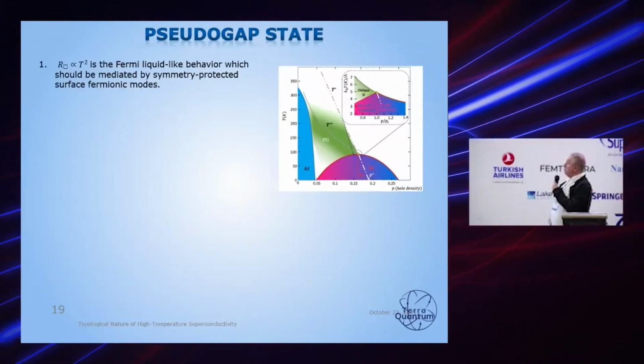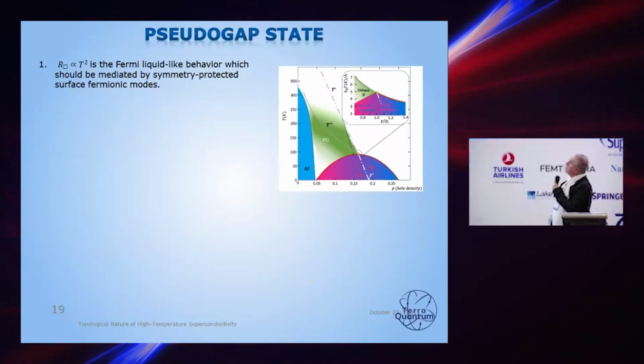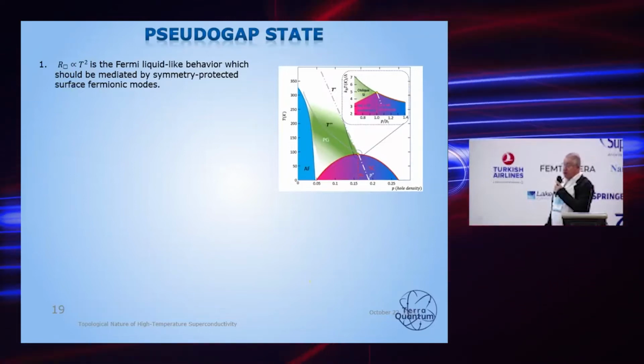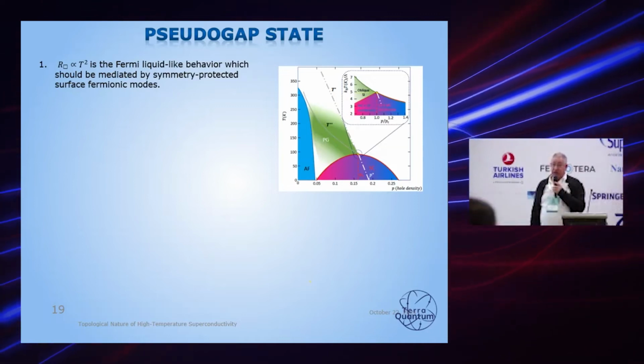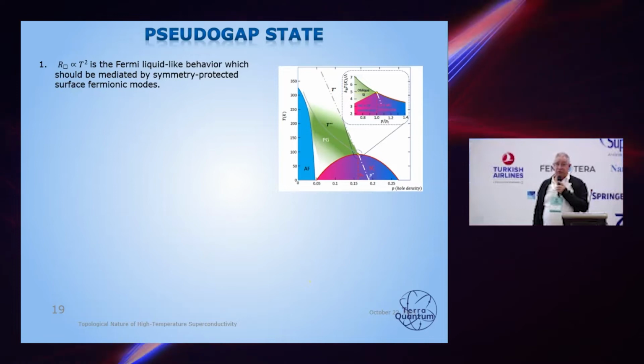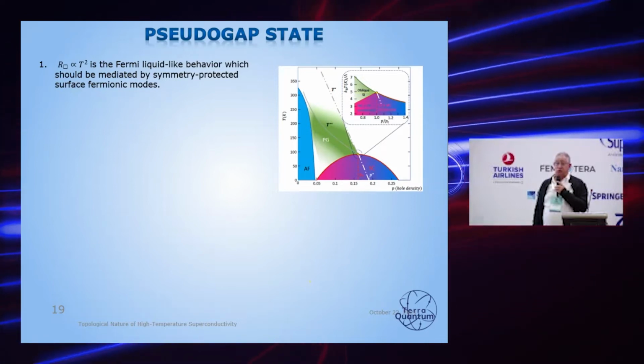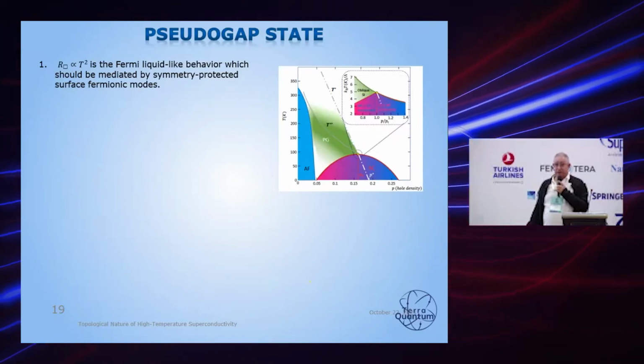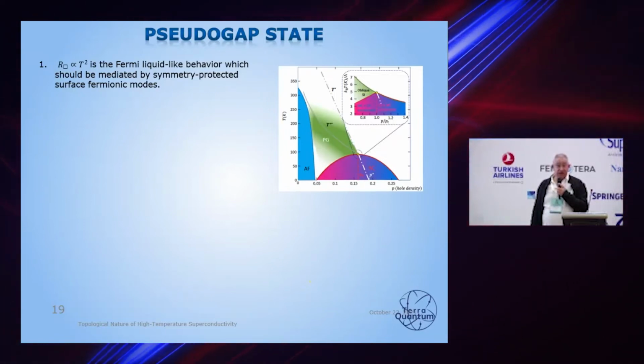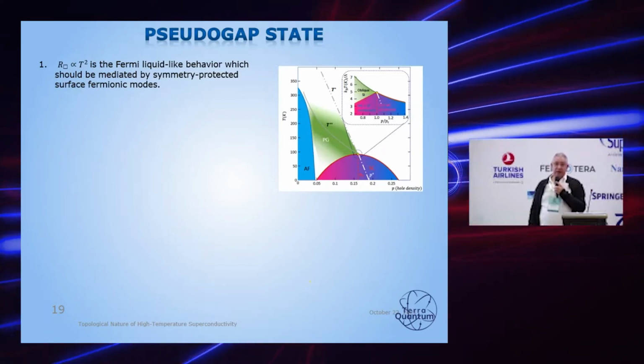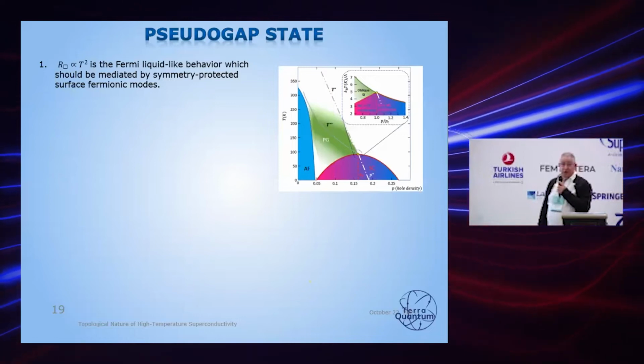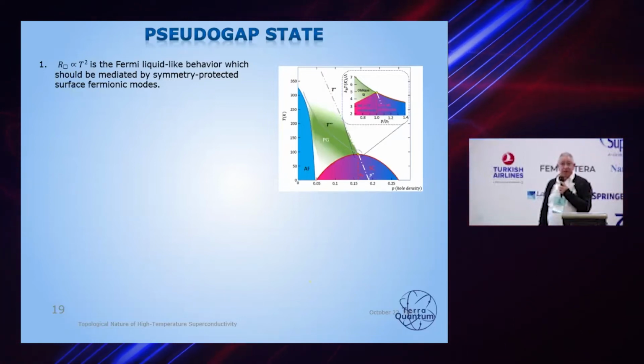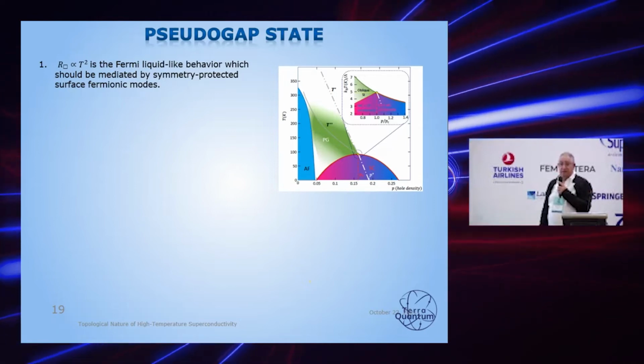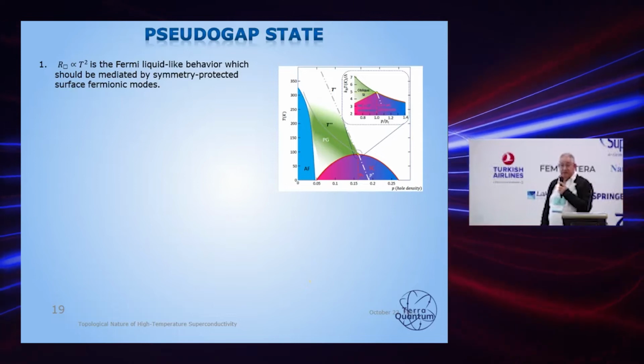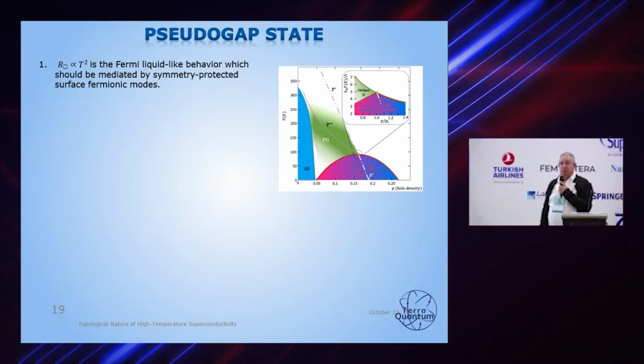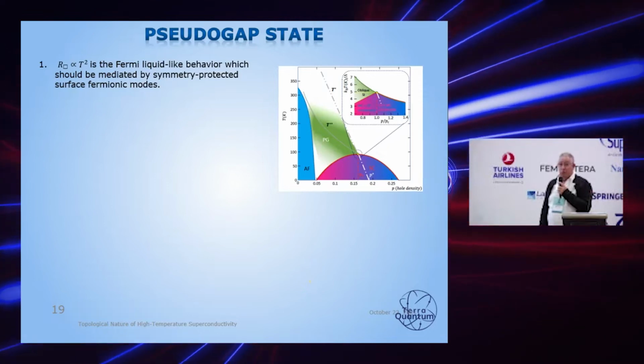Now let's turn to the pseudogap state. So let's start with this T-squared behavior. This is exactly Fermi liquid-like behavior. And what we know about Fermi liquid-like behavior is that we should have no other scatterers for these fermions but fermions themselves. Then we have this usual T-squared. It sounds a little bit strange that we can have such a phenomenon at elevated temperature. And then the only way to explain it is to say that our fermion states are topologically protected. That means that there are some surface or boundary states.